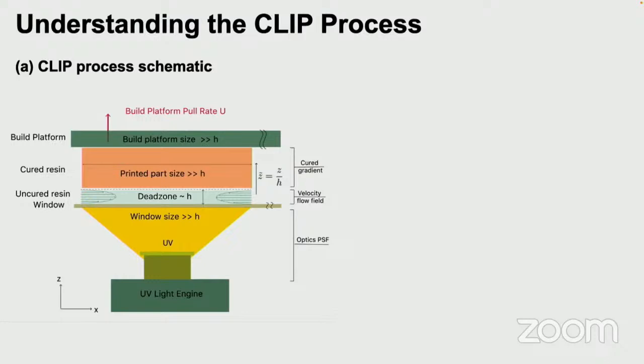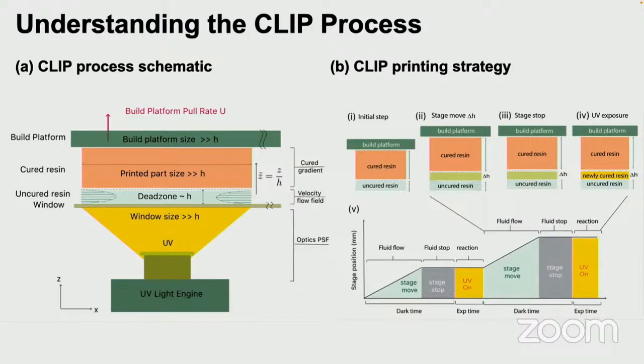And so we have this flow field driven underneath the forming part. There is a gradient of polymerization between the low viscosity monomer and the part, and there's a velocity flow field, and we control every step of the process. The printer is designed with the principles of mechatronics, where everything is sensored up, motorized, and completely controllable. So when we elevate the stage, we can elevate it at whatever rates we want. We can pause, wait for the liquid to reach quiescence, photolyze an image, and then repeat the process. This can happen very quickly, and we're basically playing a movie frame by frame, okay?